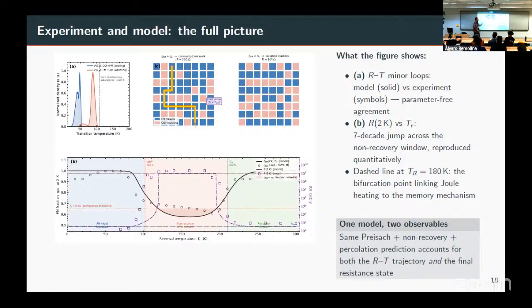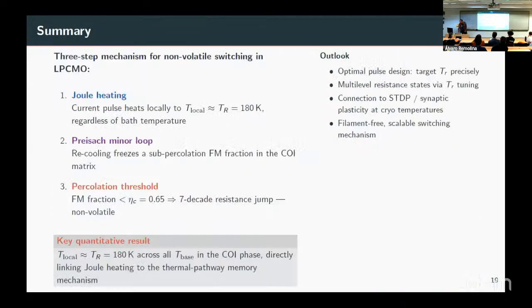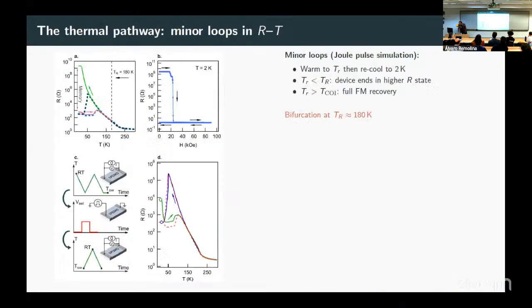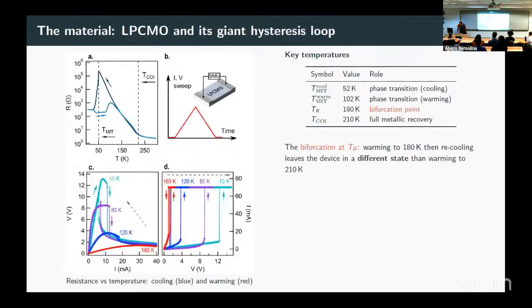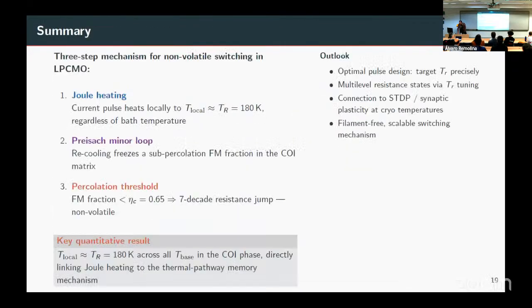So the picture here is that by calculating this Preisach model, I can show that for some particular regions, what you end up with at low temperature is a region where you either have a percolation threshold or you don't, completely, and that's why you have this huge change. And the message here is that you can use this truncated percolation model as a memory device in neuromorphic computing. And I guess I will end with that. This is my summary slide.